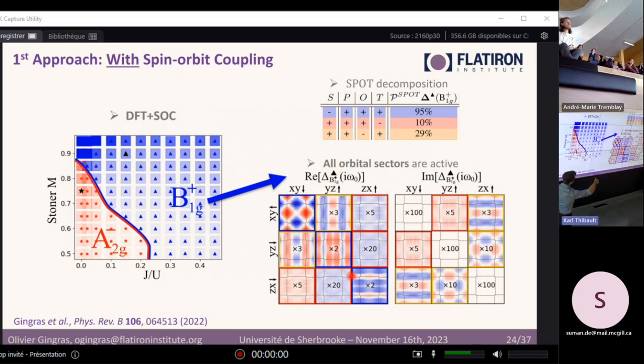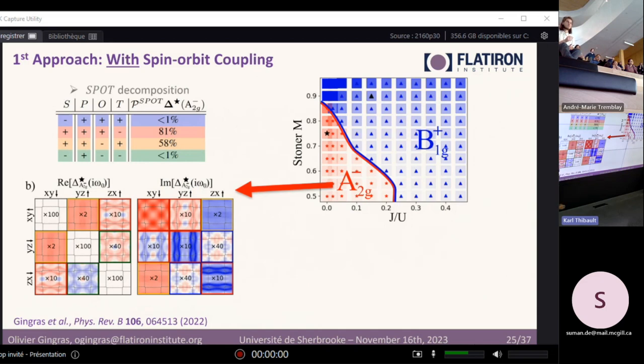This is also D wave for some non-obvious reasons. And the odd orbital part is also present and also contributes to the B1G. So this is really just a D wave generalized for spin orbit coupling. And this other state here, the A2G minus in red, is a spin orbit coupling generalized odd frequency state. So what you can see is that these are the main odd frequency components, which contribute to a large portion of this superconducting state. And there are important also odd orbital components.